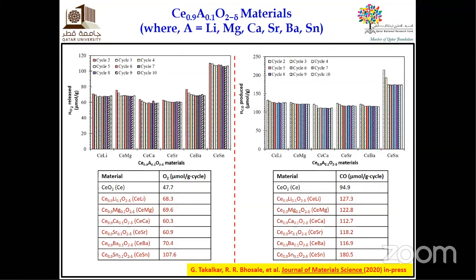Especially if you check, the tin has the highest amount of O2 released and CO produced as compared to all the dopants we have used until now: transition, lanthanide, and this. So based on this, we identified that now we are taking this to the next level to find out which materials will behave better in the pilot scale reactor, which I will show later actually. So this is the initial study we did for the ceria.